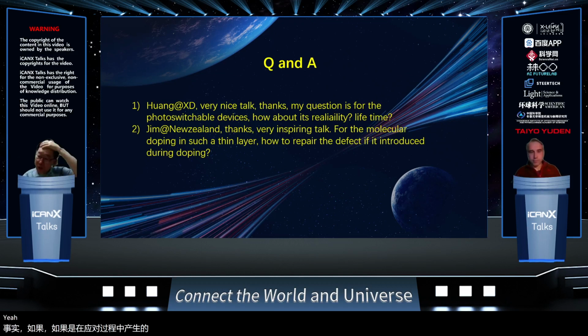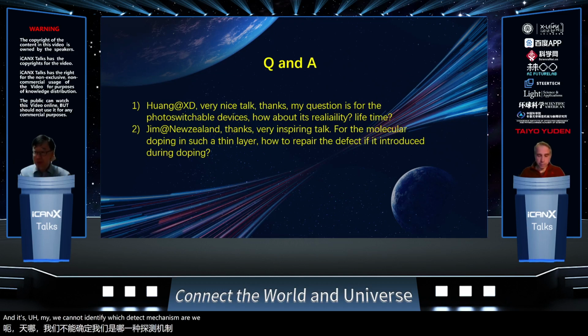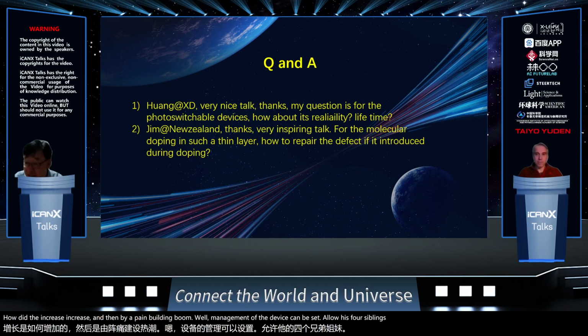Yeah, so there's a substrate defect, a bottom defect, and there's a molecular structure defect, and we cannot identify which defect mechanism is responsible whenever some defect phenomenon is observed in measurement. But let's say a metal filament is formed within the molecular junction. You can remove it by opposite polarity, though sometimes it works, sometimes it doesn't. So I think it's a repair mechanism. It's not absolutely controllable, but it is not impossible. By training the device, sometimes the current increases, and by applying more measurements, the device can settle down and stabilize. It's all possible.